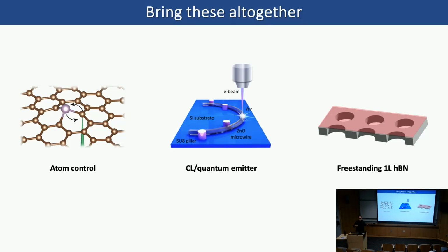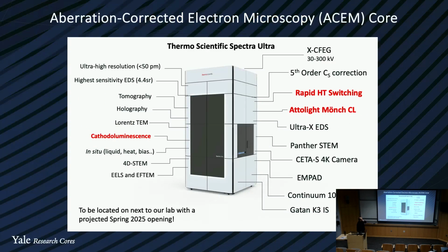But that requires a pretty high-end machine for us to do that. So this is at Yale, where we're getting, hopefully by the end of this year, a pretty good S/TEM with a very high spatial resolution, better than 50 picometer. But what's special about the Spectra Ultra is that it has a laser injection capability. There is an Attolight Mönch CL. It's a parabolic mirror that goes above the sample. So we could do laser injection, we could do CL, and we could also, in principle, do PL in there.